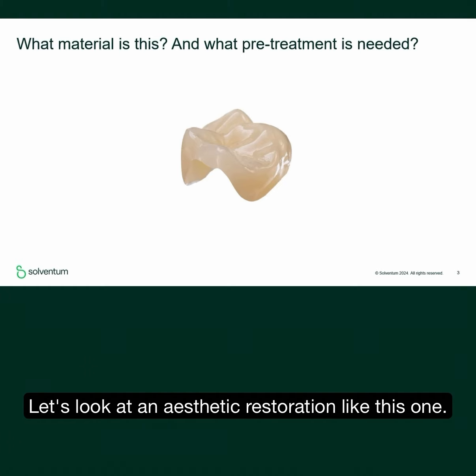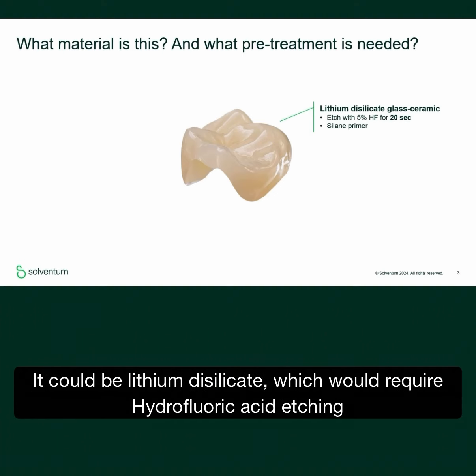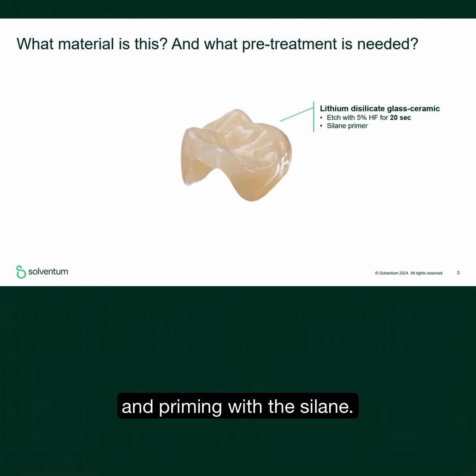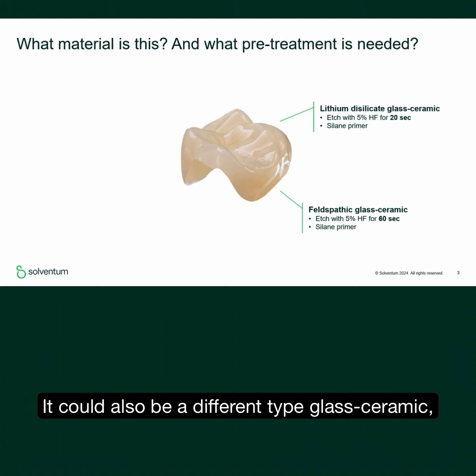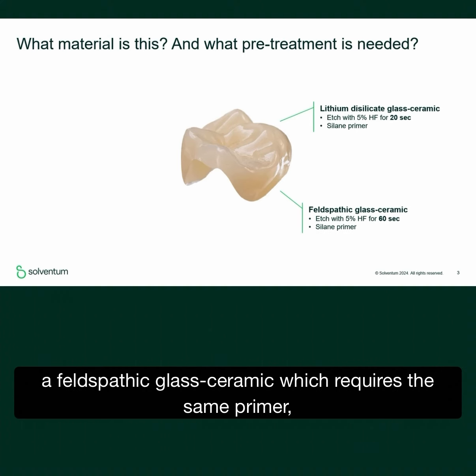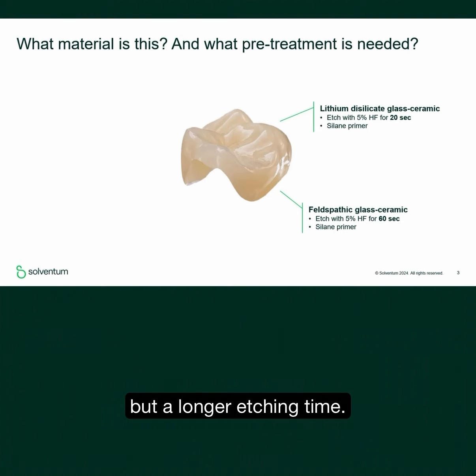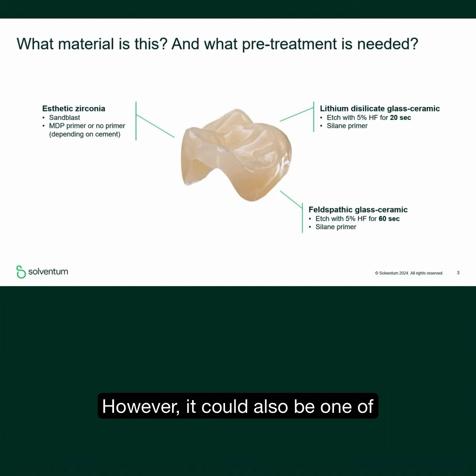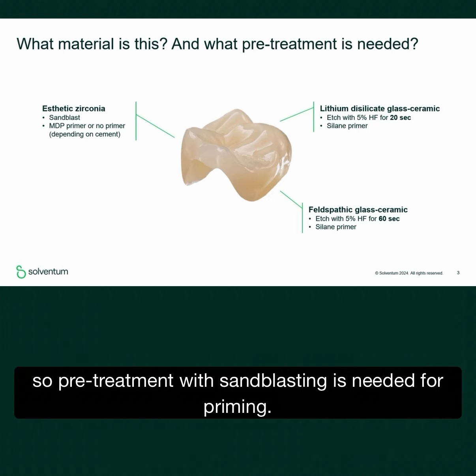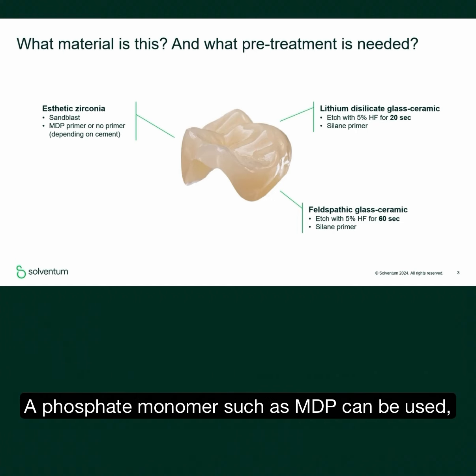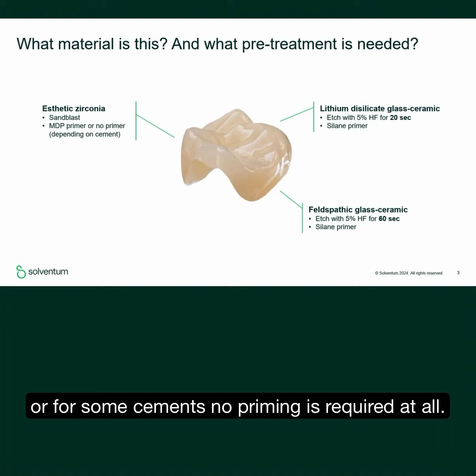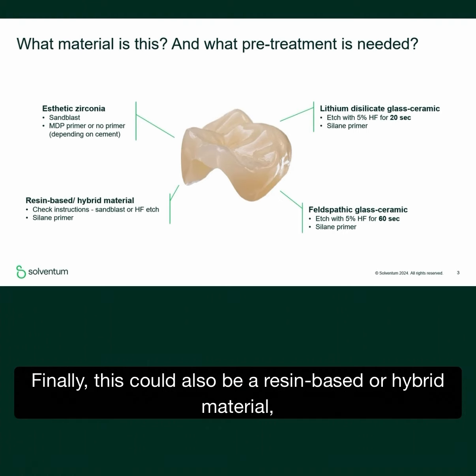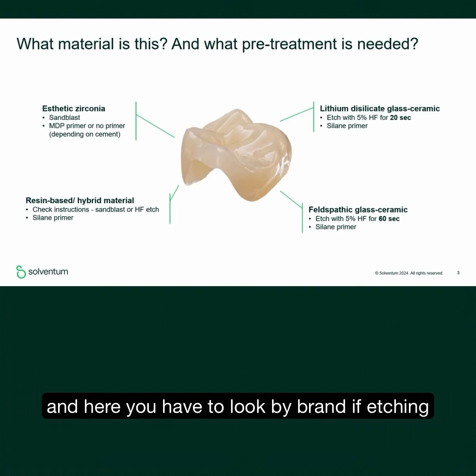Let's look at an aesthetic restoration like this one. It could be lithium disilicate, which would require HF etching and priming with the silane. It could also be a different type of glass ceramic, a feldspathic glass ceramic, which requires the same primer, but a longer etching time. However, it could also be one of the highly translucent aesthetic zirconias. Here, etching has no effect, pretreatment with sandblasting is needed. For priming, a phosphate monomer such as MDP can be used, or for some cements, no priming is required at all. Finally, this could also be a resin-based or hybrid material, and here you have to look by brand if etching or sandblasting is the right pretreatment.